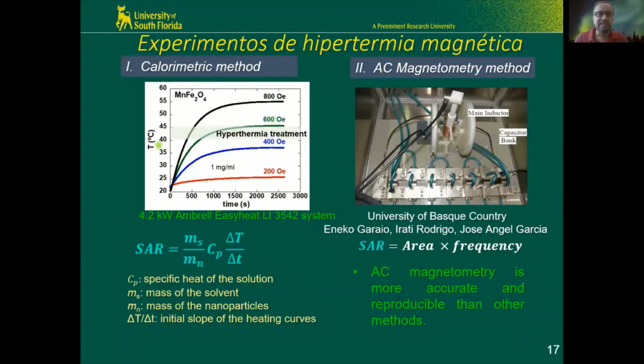Now from this, you can see that that's the hyperthermia window, right? 40 to 45. So ideally, you want the heating to be really fast and then basically stabilize in this window. You don't want to overheat it. There's no reason for that. And if you don't apply enough field, you will never get here, okay? But by looking at, in this case, these are manganese ferrite nanoparticles. For different kinds of particles, you can find out exactly what are the parameters needed, what frequency, what field is needed for it to stabilize or saturate in this temperature. By the way, this saturation is simply because of heat exchange, latent heat, and the specific heat of the medium in which the cells, in which these particles are.